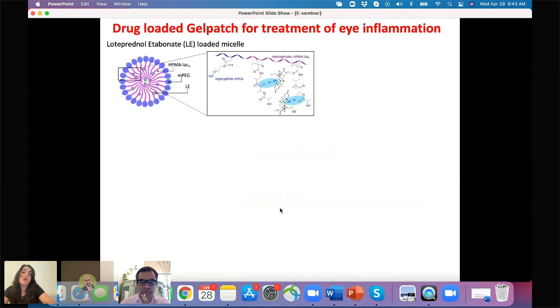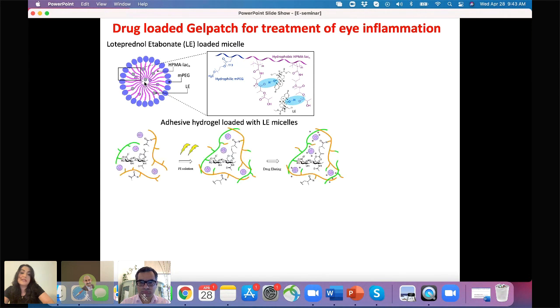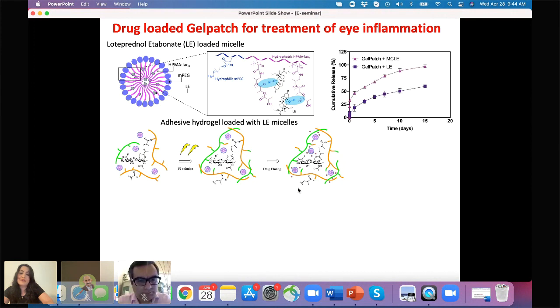And then once we form gel patch with optimized formulation, we also work on engineering micelles loaded with anti-inflammatory drugs. So here we use loteprednol, LE, that this is a hydrophobic drug that is incorporated inside these micelles. And once we form these micelles, the micelles were combined with our hydrogel formulation and photocrosslinked to form these drug-eluting biomaterials. We look into the release profile of the drug from these hydrogels.